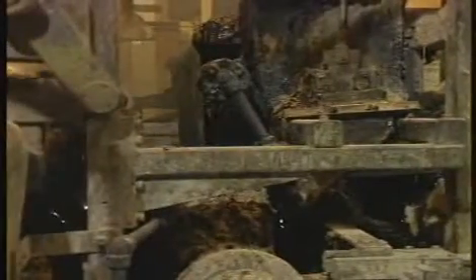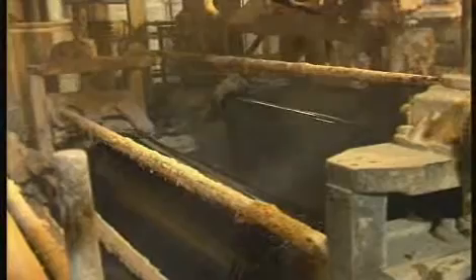The felt first runs through very hot bitumen, which saturates the fabric. The fabric is then squeezed through rollers to consolidate the impregnated felt and remove excess bitumen. It's then coated on both sides with cooler bitumen to produce roofing felt of the required thickness.